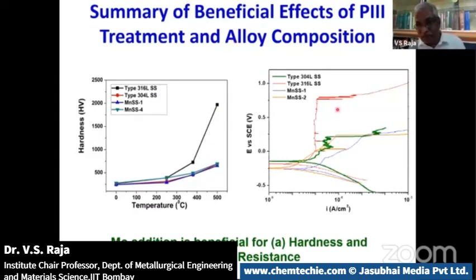This is something which we discuss using the electrochemical polarization curve. It tells how good the material is. For example, what's shown in this curve is potential versus current. What you see here is that when I raise the potential, the current does not increase. We call this the passive region. See, so nice. The stainless steel has a huge amount of passivation taking place because of this. Again, not all the stainless steels are the same, right? 316, 304, and manganese-containing stainless. Not all of them behave in the same manner.